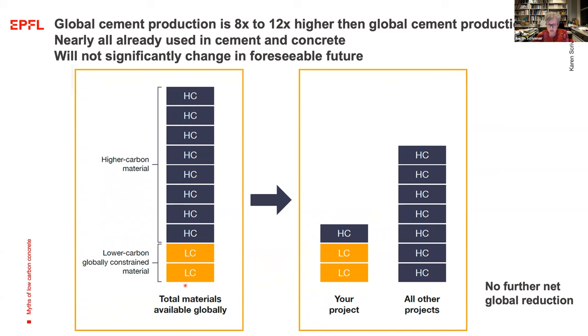So you can either spread that 10% out across all concretes, or somebody can say, well, I want to go to a very high level of slag replacement in my project. Well, the consequence of that is that you take slag away from all the other projects. And in terms of the global CO2, which is, of course, what we care about, you have no net further reduction. So this is a very important point. It really doesn't help by increasing levels of slag replacement.